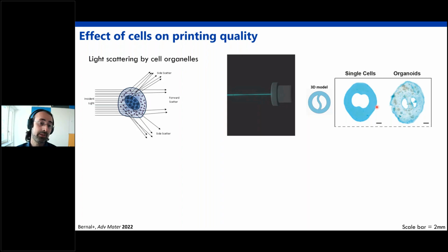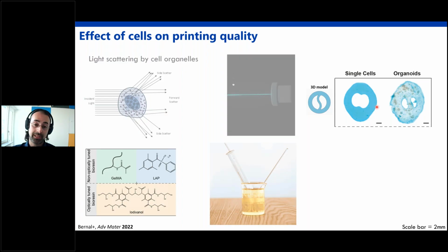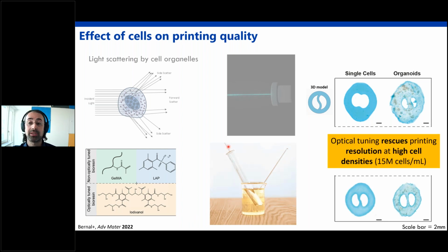So the solution we came up with is much like Jordan showed, the possibility to edit the rheological properties for extrusion. In light-based printing, we look at ways to edit the optical properties of the material. And we do that by adding a compound called iodixanol, which is a biocompatible refractive index matching agent that essentially makes some of the most scattering elements in the cells, specifically the nucleus in this case, transparent to the light that we are working with, so that we can then actually restore a resolution with about 15 to 20 million cells per ml already in our structures.